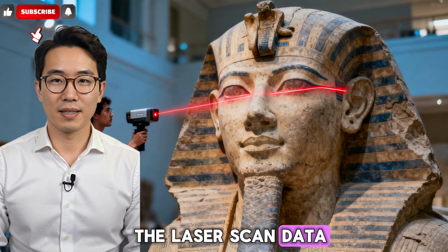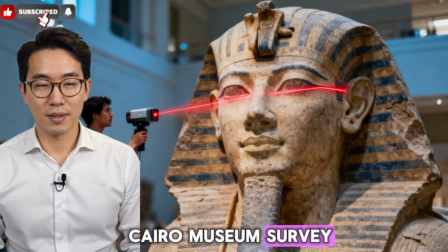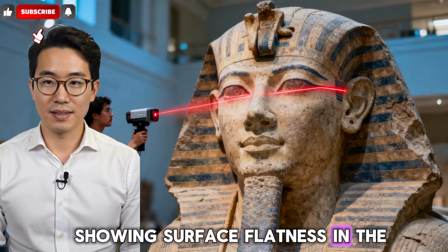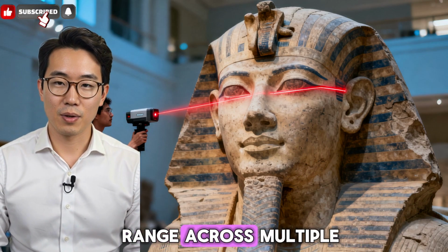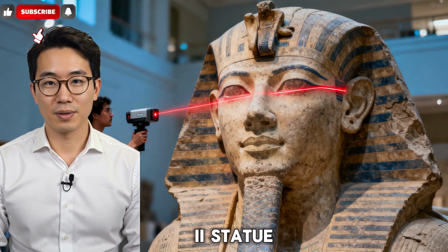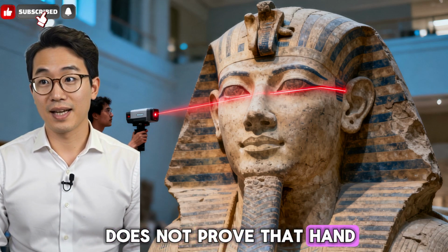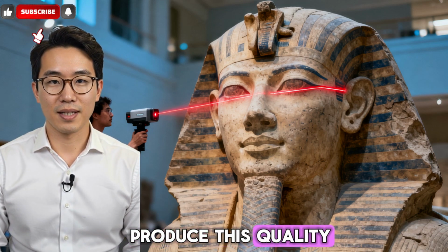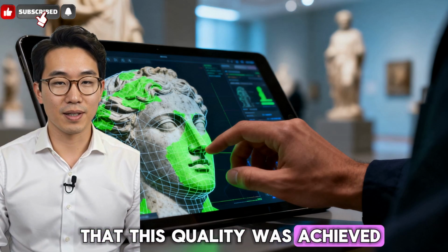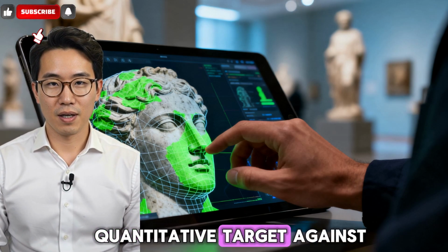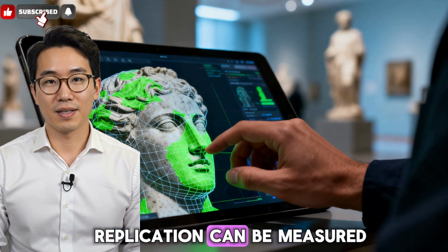The laser scan data from the 2019 Cairo Museum survey, showing surface flatness in the sub-tenth of a millimeter range across multiple locations on the Ramesses II statue, does not prove that hand lapping cannot produce this quality. It establishes that this quality was achieved, and it provides a quantitative target against which experimental replication can be measured.